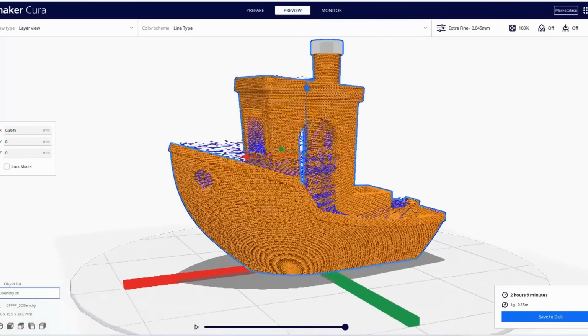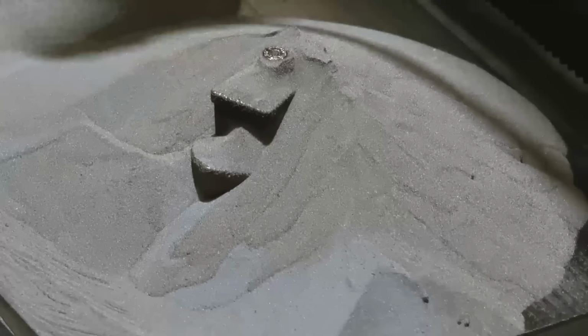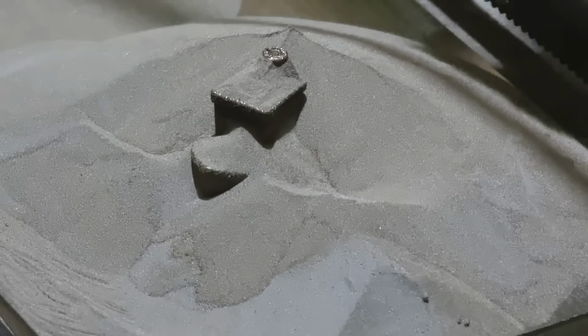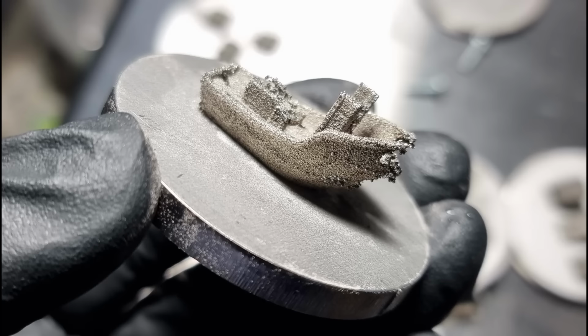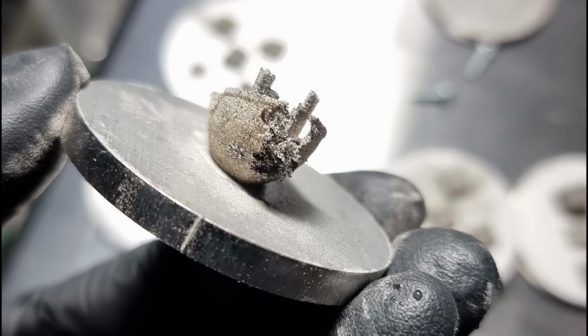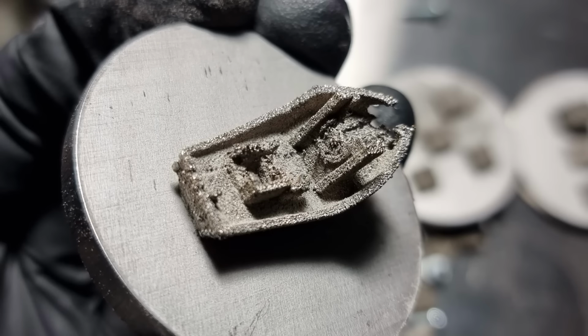The final thing I wanted to print before calling it a day was a benchy. The print volume is very limited, as this is very much a proof of concept, but it could still handle a benchy at 50% scale. It would take 5 attempts before succeeding, with the first failing due to there still being some undiscovered issues with my controller, leading to a double application of powder, causing a lack of fusion and some areas to just crumble away.